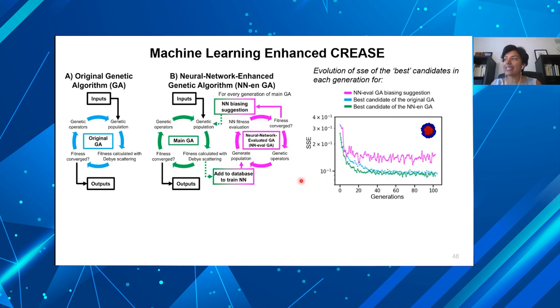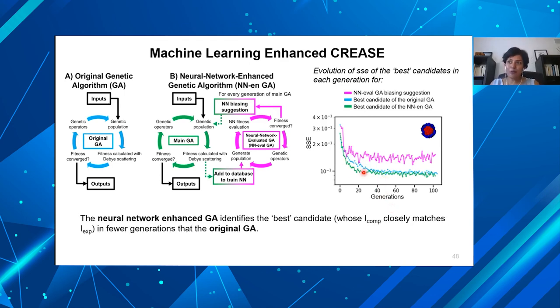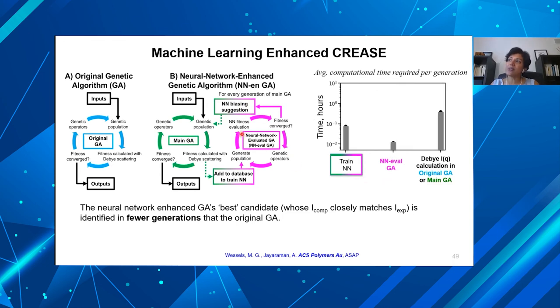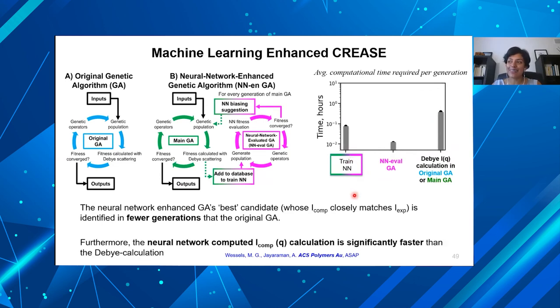And the side suggestion apparently makes a huge difference. This quick side calculation with the machine learning allows us to converge to answers fast. Not only fast in fewer generations, but also if we just wanted to use that side cycle, that has much faster speeds of calculation than if you ran one generation of this original genetic algorithm or this combined loop. So if you invested time in developing a really good machine learning model, you can just use that and run just this pink cycle, and you'd get answers really fast. So that's something we are suggesting to our scattering colleagues at NIST, and that's why we ran the symposium yesterday with folks at NIST who manage scattering.